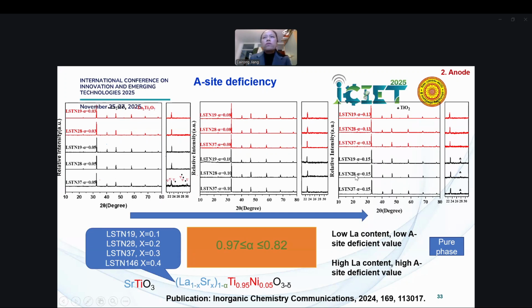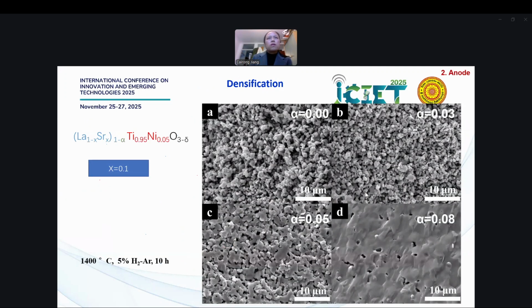But if you increase the lanthanum content, like 30%, and here the black one, 40%, we really need a high value of A-site deficiency. So this means you can tailor the deficiency to get the desired material. We're showing here different values. You increase a bit to get pure materials, and the density of these materials could be different too.